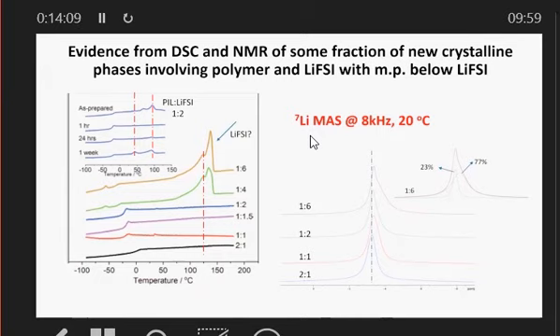Now, this is not the LiFSI crashing out, precipitating in the polymer. It's actually new phases being formed. And those of you who can remember the PEO-based systems, and you look at the old Colin and Vincent book on polymer electrolytes, you'll find that PEO with salts forms multiple phases. And so I think this is what's happening in this system. We're forming different phases of the polyIL with the lithium salt.